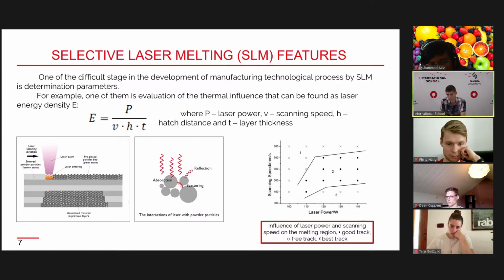For aluminum, it's for example 50 joules per cubic millimeter. For titanium, it should be greater, to melt it. And also we have to find the balance between these parameters, because if we put in too much energy, we can maybe even evaporate the material, so it will not even melt on the plate. In the process, the metal powder secures the absorption of energy. It can reflect some percent of the energy, and scattering occurs.